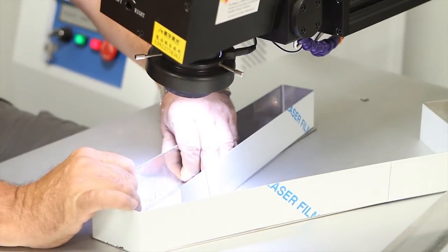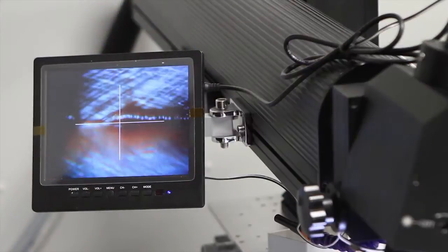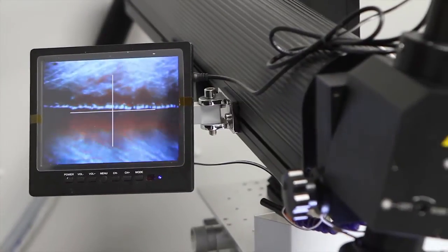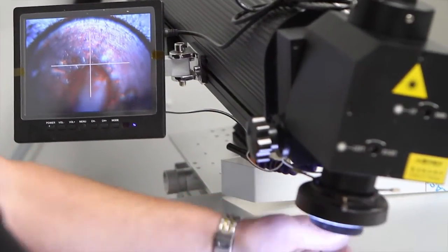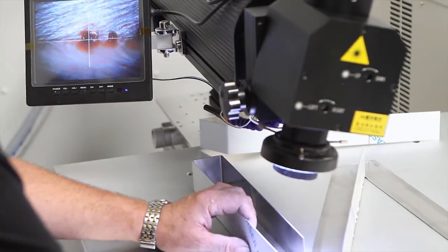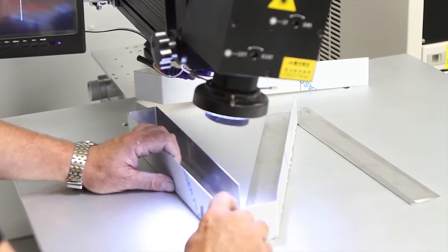We can use stainless steel of 0.7 to 3mm thick. Letters created with the laser welder can withstand powder coating processes up to temperatures of 170 degrees to 190. This means there is no need for high temperature solder.